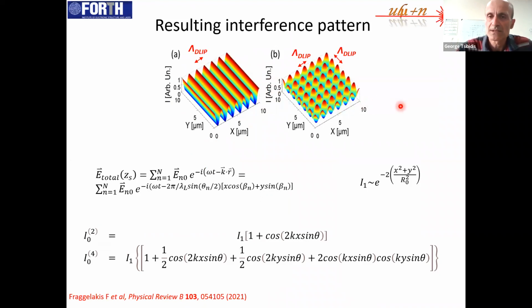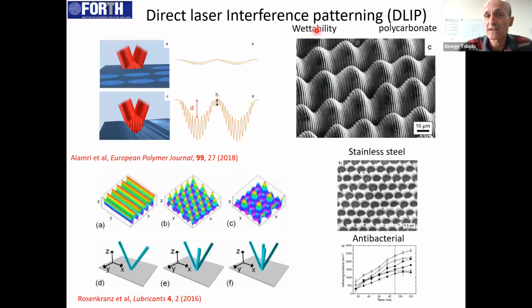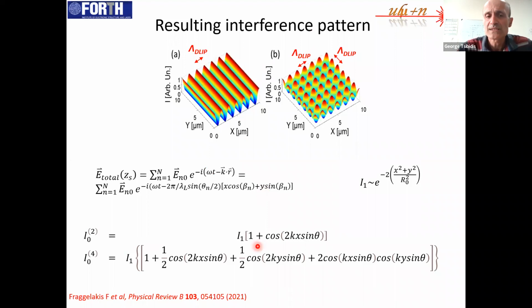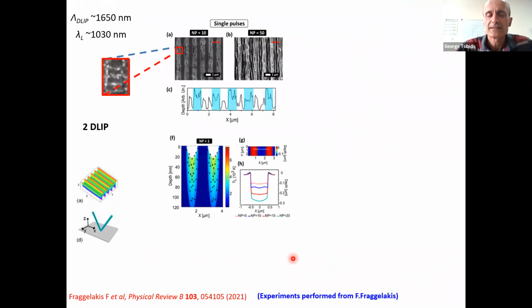This scheme is called direct laser interference patterning. It's called DLIP. So this is the intensity after using two beams, and this is after using four beams. What is interesting is we can produce periodic structures by exploiting this periodicity in the intensity profile. So you see here the fingerprint of fluid dynamics.